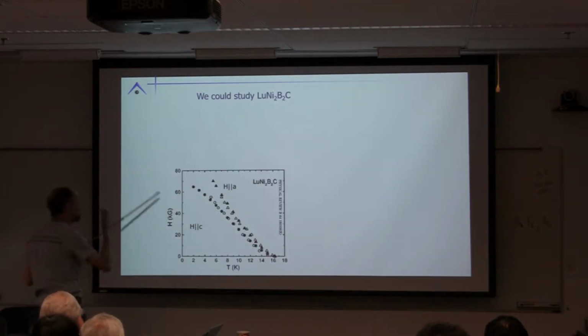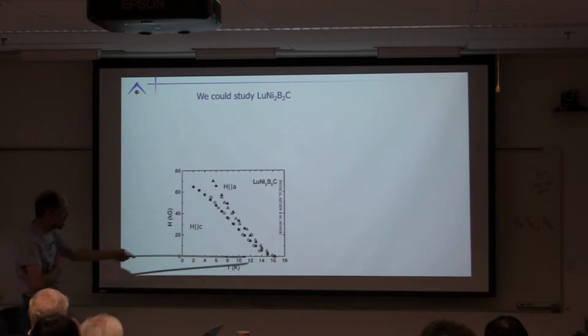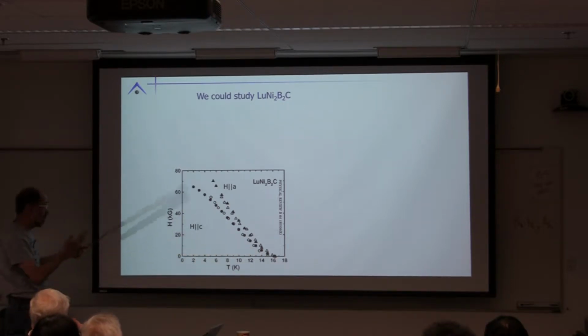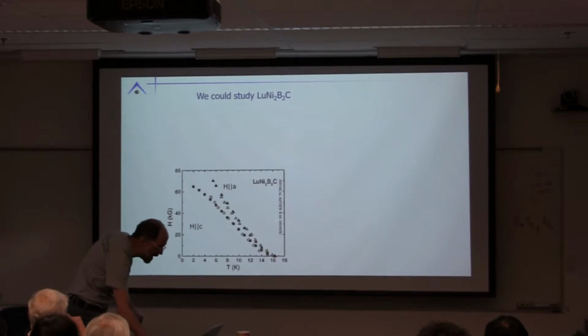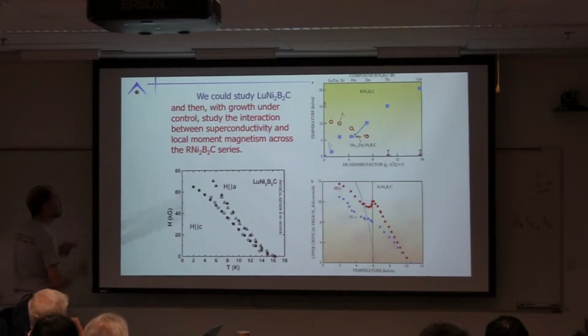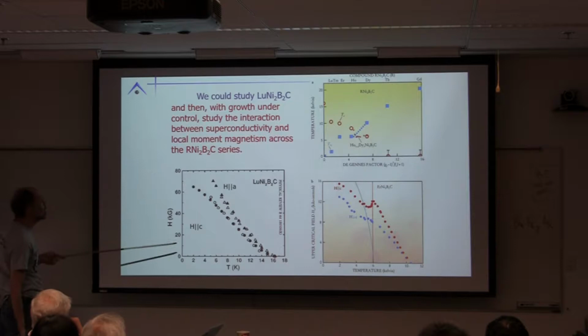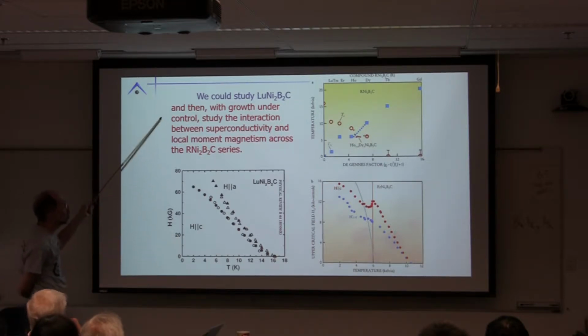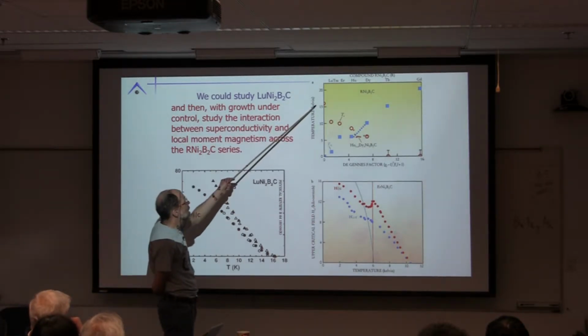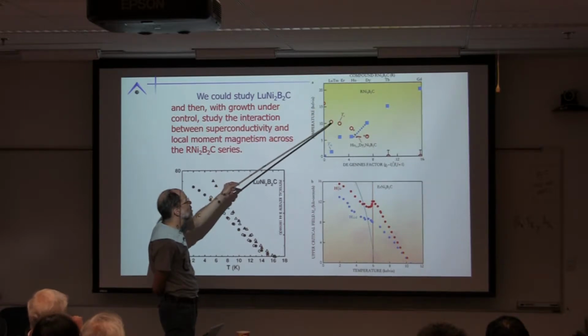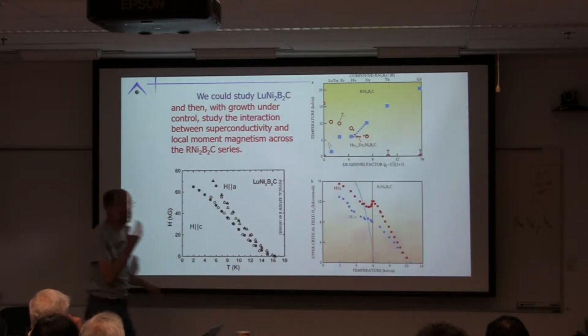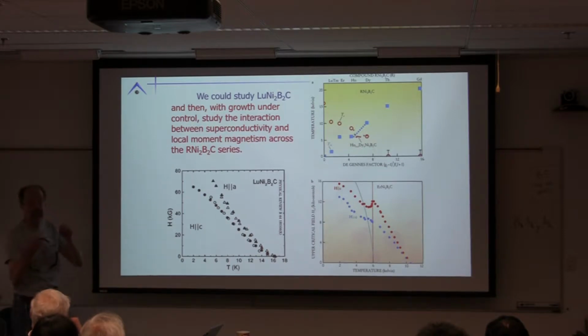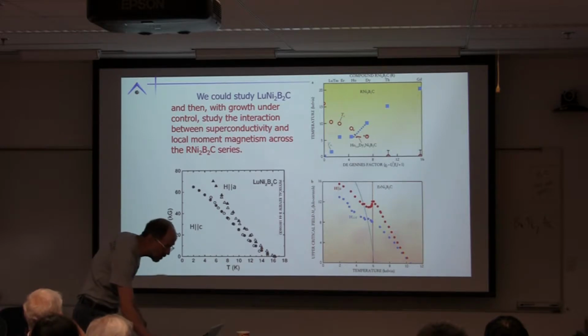Now, lutetium-nickel borocarbide, which is what we originally wanted, has a TC around 17. It has a relatively isotropic, but also disappointingly low Hc2. It was sort of cute. But on the other hand, having mastered the growth of the lutetium nickel borocarbide, it opens up the possibility to look at all the other rare earths, and you can form this material for non-magnetic lutetium or yttrium, but also magnetic thulium, erbium, holmium, dysprosium, and you can look at the interactions of local moment magnetism and superconductivity. Okay? And that was a wonderful way to play around with these materials.